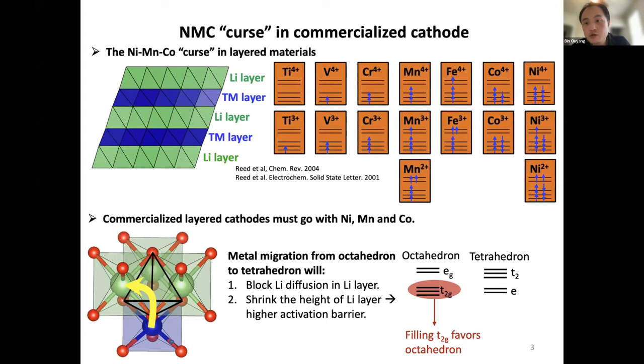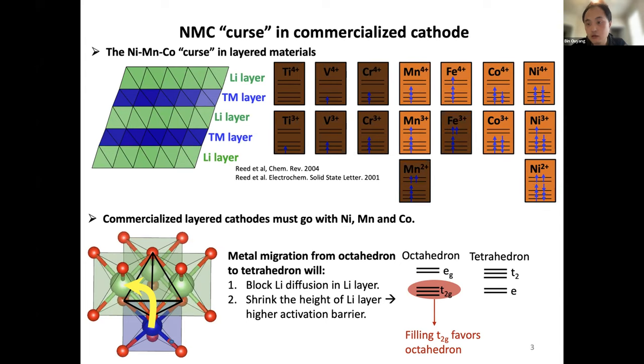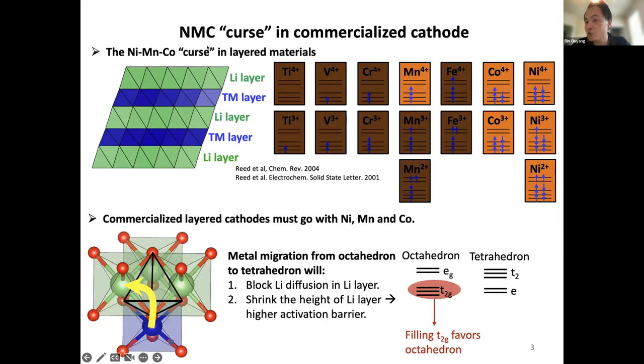Looking at all the 3D transition metals: titanium, vanadium, and chromium are bad choices because when oxidized they have fewer than three electrons and will migrate. Mn²⁺ and Fe³⁺ have high spin states with all D orbitals occupied and will go everywhere. Mn³⁺ and Fe⁴⁺ don't have this issue, but unfortunately they are Jahn-Teller ions causing structural distortion. So eventually what we have is Mn⁴⁺, which is redox inactive. For redox action we only have cobalt and nickel — this is the chemical origin of the NMC curse for layered cathodes.